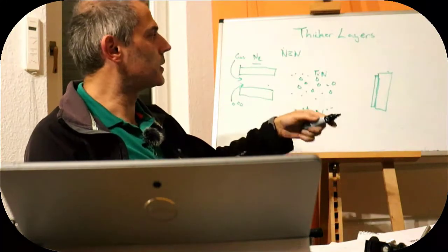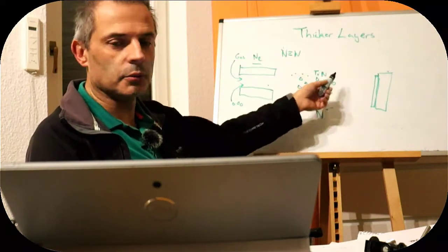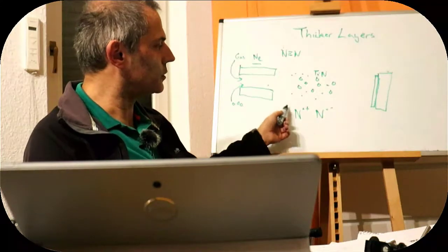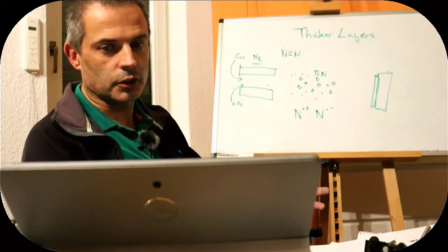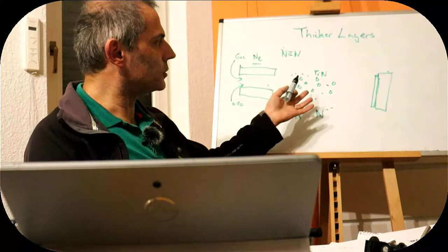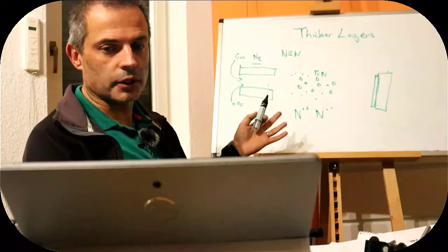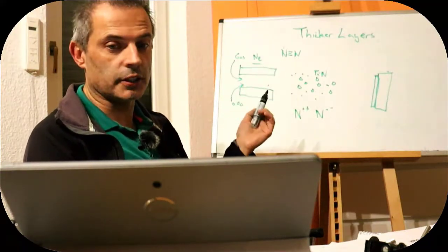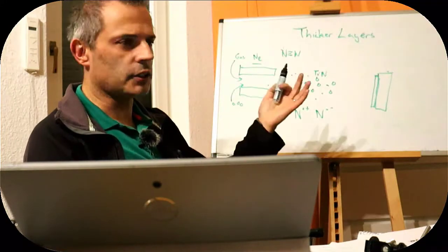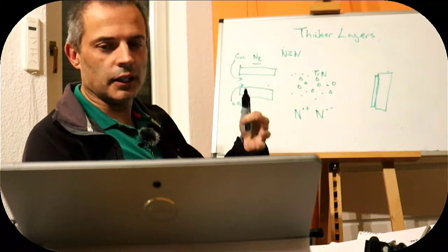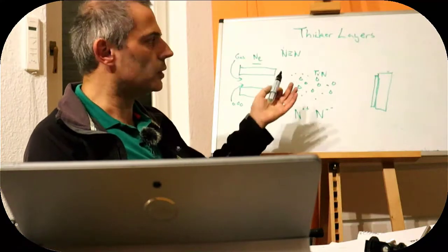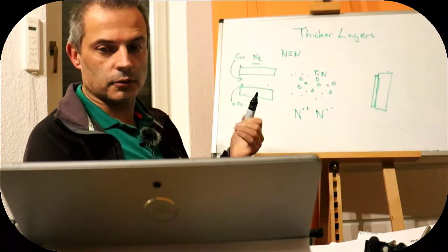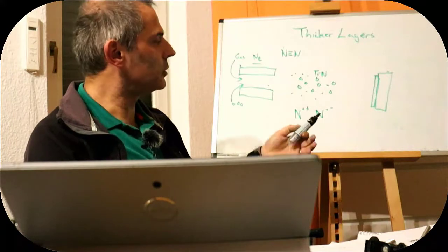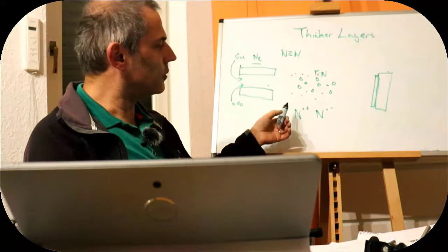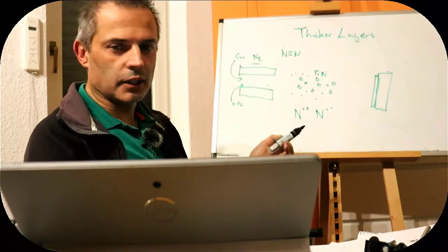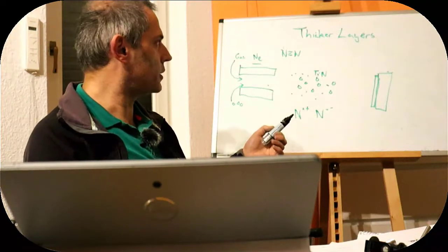the surface. So if we've taken our titanium, we've lost a little bit of nitrogen, new nitrogen, one of these ones can bond to it, and that dumps a lot of energy in. The typical temperature for this is over 2000 degrees. If we take a piece of titanium and nitride it by just setting it on fire in nitrogen, it will burn and heat up on its own to over 2000 degrees. So that's good because we get all of that energy back out, and likewise we can get the energy of nitrogen recombination out if we don't have any open bonds left over.